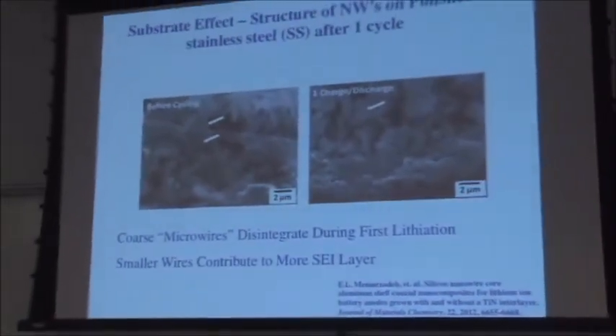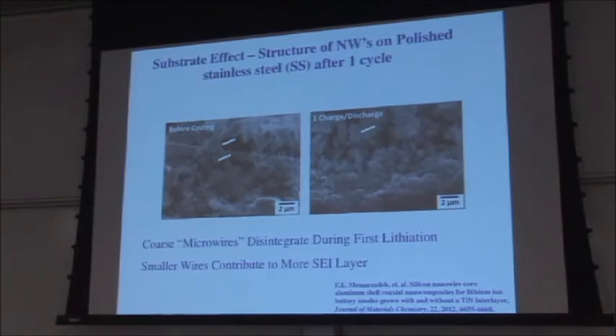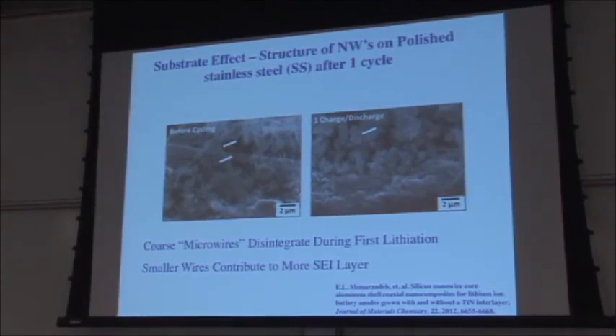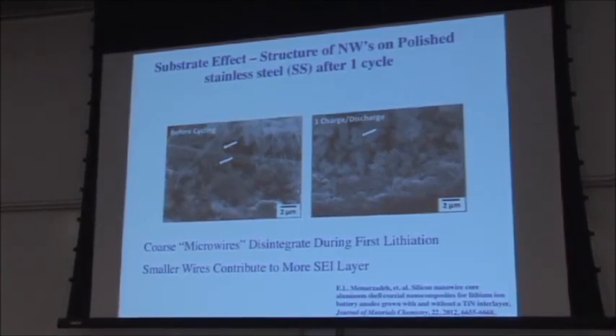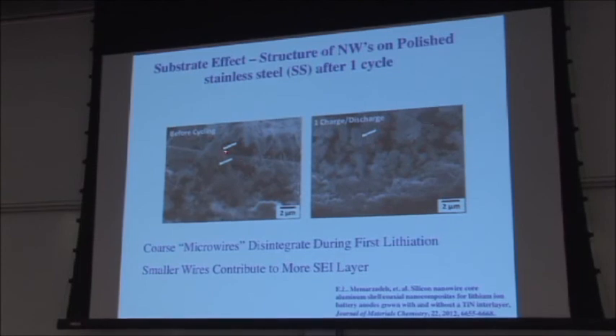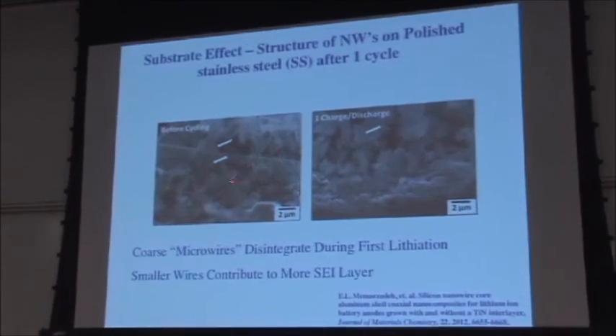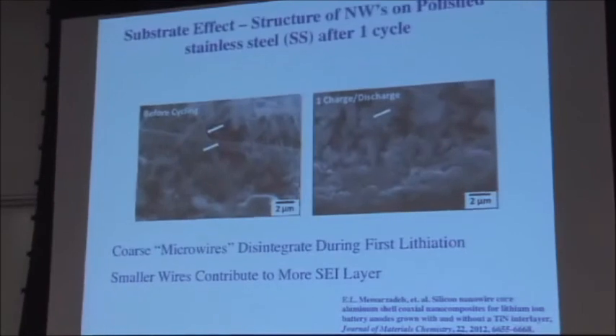So when we looked at this microstructure, it's kind of a messy slide, but it really highlights things well. So you get these, again, microwires, very fine nanowires, and really this is first charge, discharge. Look how messy this looks. These big microwires are all entirely detached from the substrate. So you lose close to 17% capacity in cycle 1 simply due to catastrophic failure of the coarse particles and significantly more SEI layer formed.